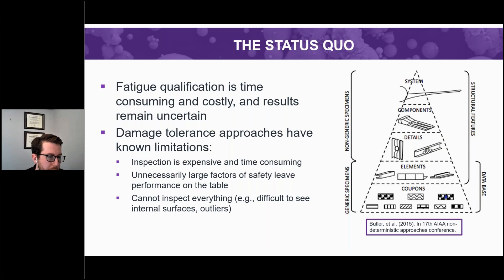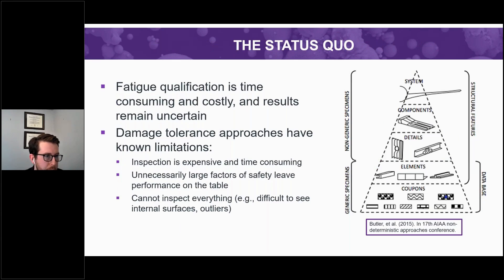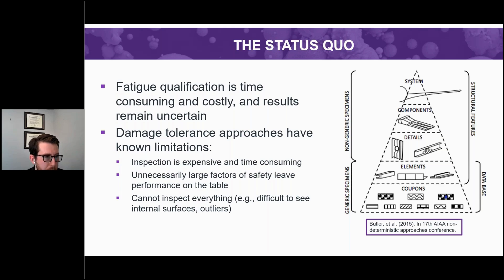As a result, the status quo is to make compromises. We make best efforts to predict minimum fatigue performance, and then we take a damage tolerance approach, whereby we inspect parts in service to determine if a crack has initiated and, if so, how much longer the service life can be. This approach works, but it does have limitations. Particularly for high-cycle fatigue, the majority of fatigue life is consumed in just initiating the crack at the microstructural scale, which is not well captured by non-destructive evaluation. Additionally, inspection is expensive and time-consuming, and we can't inspect everything — internal surfaces and complex systems cannot always be inspected. This approach results in low certainty, necessitating very high safety factors, which reduce performance inherently.